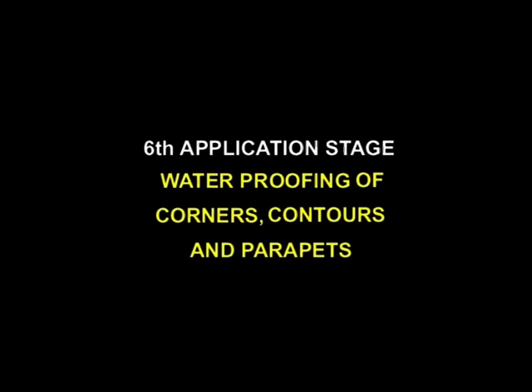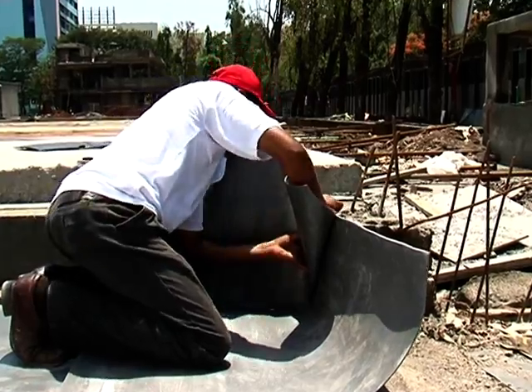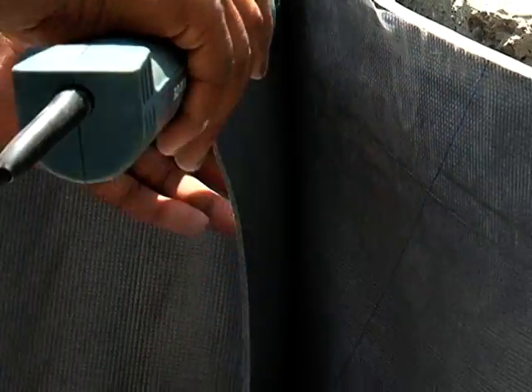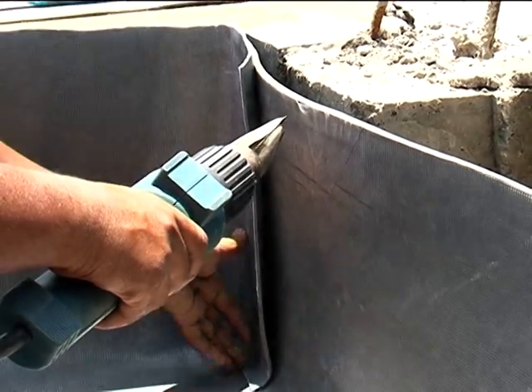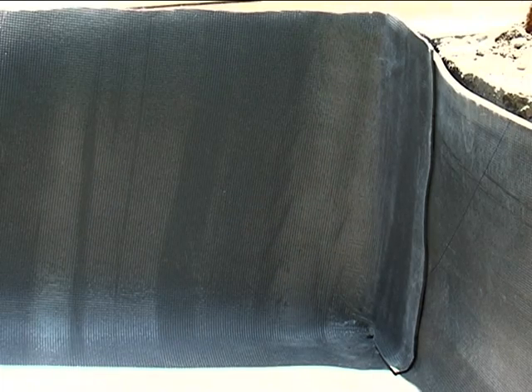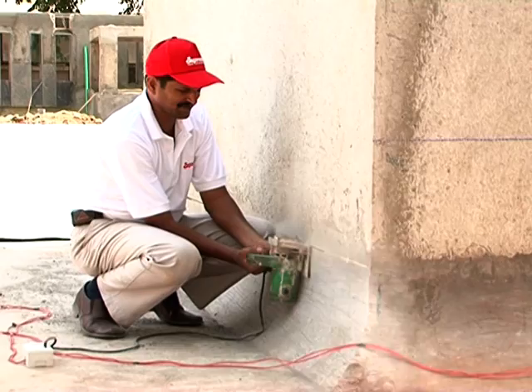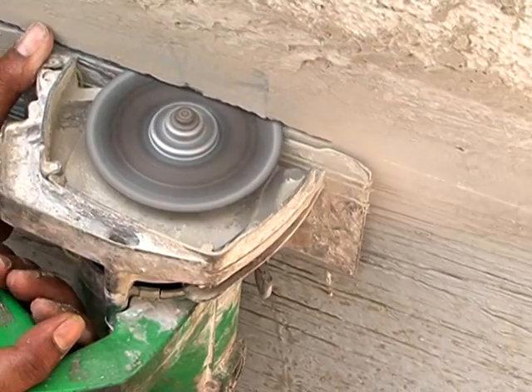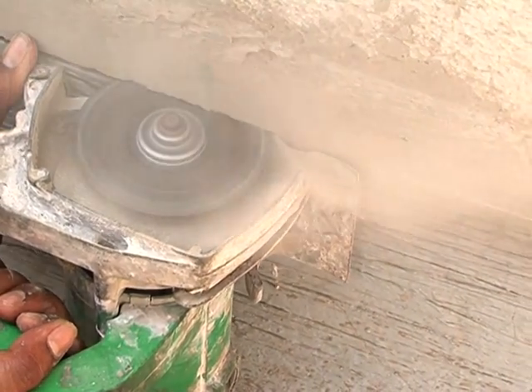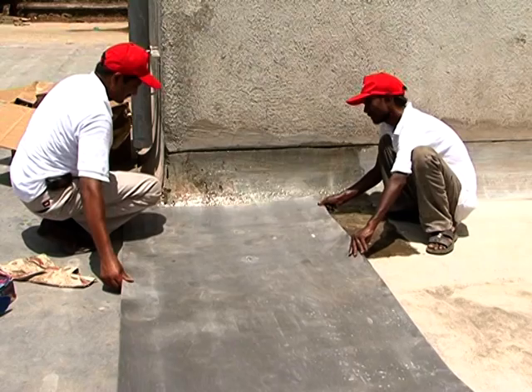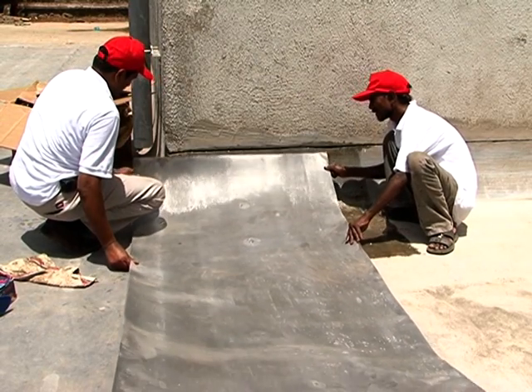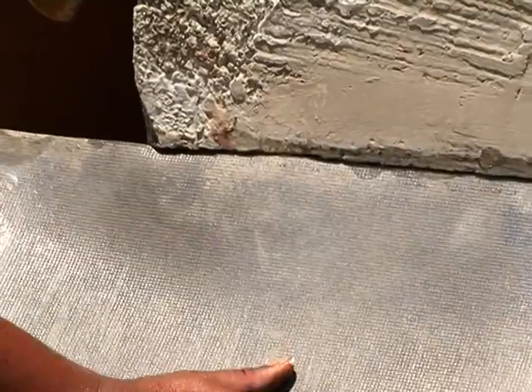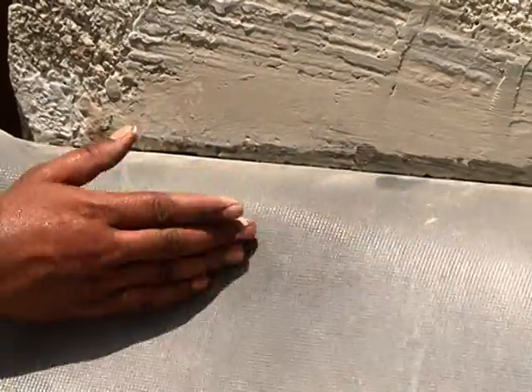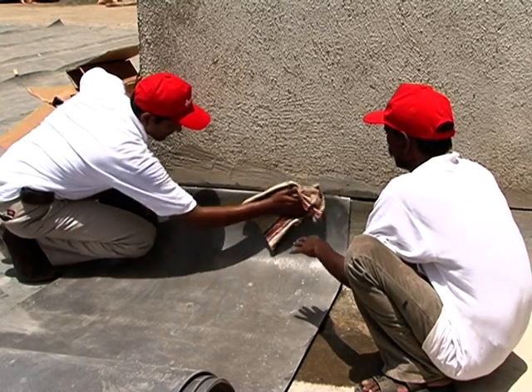Sixth application stage, waterproofing of corners, contours and parapet. At the corners, the membrane is cut and sealed by overlapping. This ensures a long-lasting durability and also gives it a perfect finish. For contours and parapets, cut a groove of 10 mm into 25 mm on the wall. The membrane must be taken above the contours and terminated 6 inches to 8 inches vertically on the parapet wall and inserted into the groove.